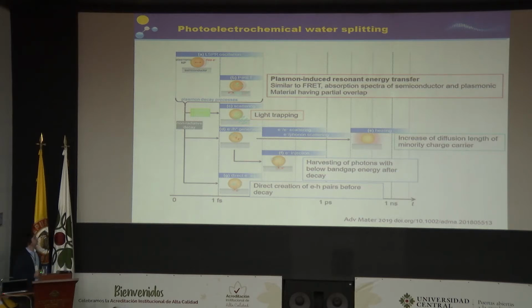What we can do also is use what happens after the dissipation of the surface plasmon. So we can use the hot electron and hole pairs, which are generated inside the metal nanoparticles, and they can be injected in the semiconductor conduction band. These carriers should have energy higher than the Schottky barrier which forms at the interface. And this is an interesting approach because in this way we can use hot electrons which have energy lower than the gap of the semiconductor.